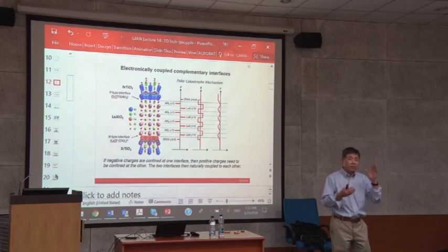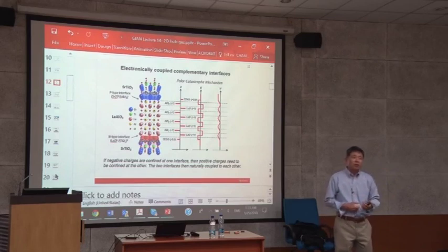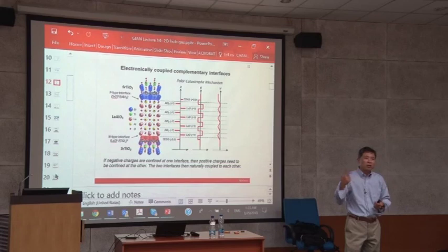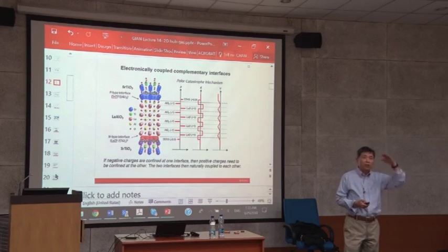And people then look at this TiO2 termination with a technique called CAICISS, coaxial impact collision ion scattering spectroscopy, which measures the top surface atoms and is the most sensitive method. They use the angle and look at the surface layer, so they confirm that the top surface is TiO2. That's one thing, and that is the substrate. Then the second layer, the top layer, is what you grow.